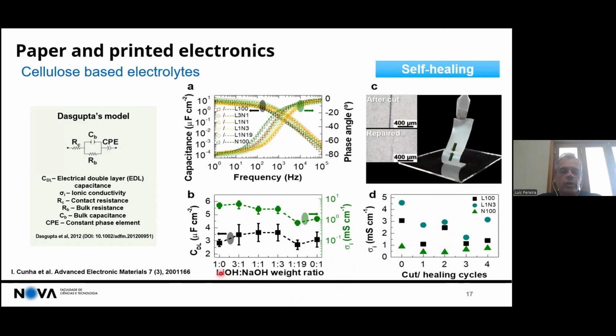We can make it with lithium only. We can mix with sodium ions as well. And the most important thing is that they present high capacitance. But if you look at these, you can already start to understand more or less the maximum theoretical operation frequency that you can extract from devices using these electrolytes. Because you see that you have a big drop in the electrical double layer capacitance when you increase the frequency. And so you see that around 1 kilohertz to 10 kilohertz is more or less where we have a big drop and these devices will no longer operate. And this is already in optimal conditions, because it also depends on the dimensions of the devices.